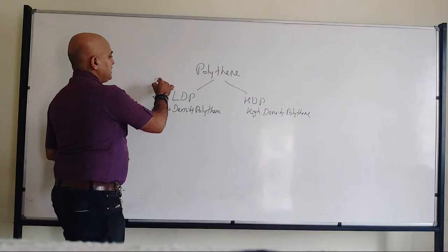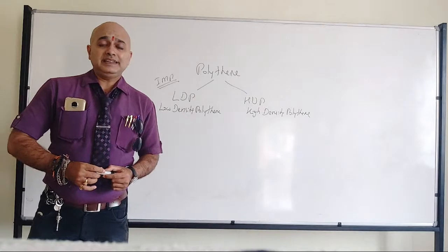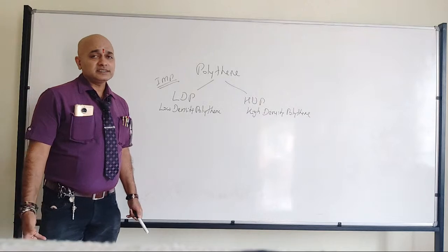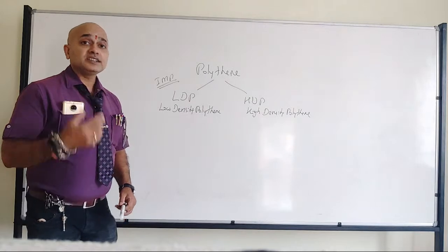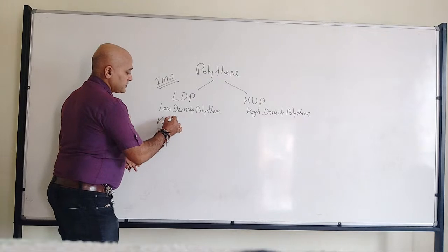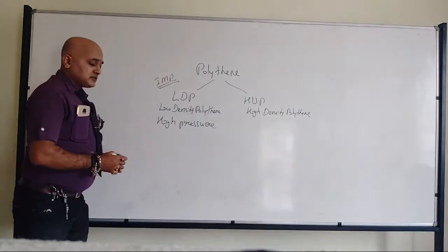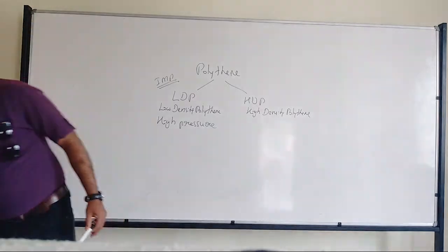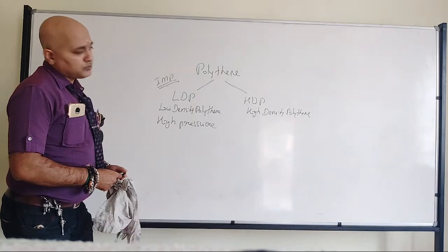This is also important. Now, when I am talking about low density polythene, here naturally radicals are required, that is peroxides are required, no doubt, for both. But along with that, the reaction conditions are different. In this case, they are going with very high pressure. It can go up to 1000 atmospheric pressure, even 1000 to 2000 atmospheric pressure.